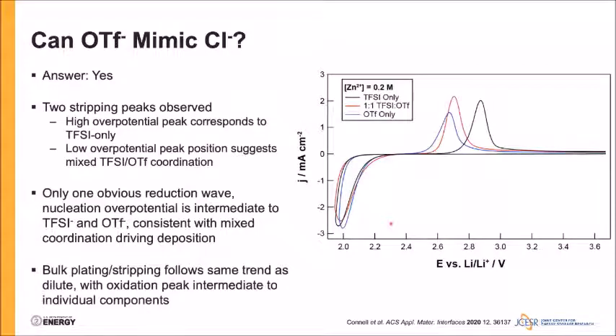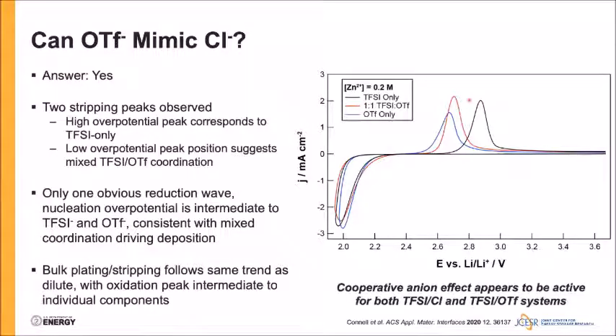Now, this isn't just relevant to the dilute case. If we look at a bulk electrolyte, a 0.2 molar zinc electrolyte with TFSI only or triflate only, and then the mixed TFSI triflate system, we see essentially the exact same trend, where we see improvement in reversibility relative to both electrolytes, and the onset of oxidation again sitting intermediate to what we see for the TFSI only and triflate only cases. And so we have very strong evidence that this cooperative anion effect appears to be active for both the TFSI chloride and the TFSI triflate systems.